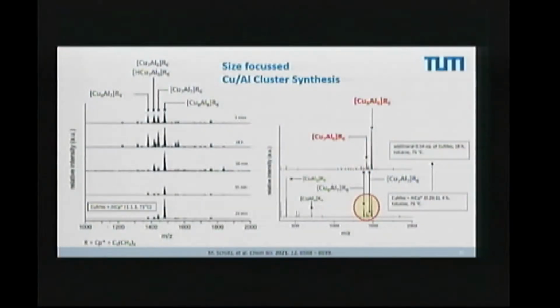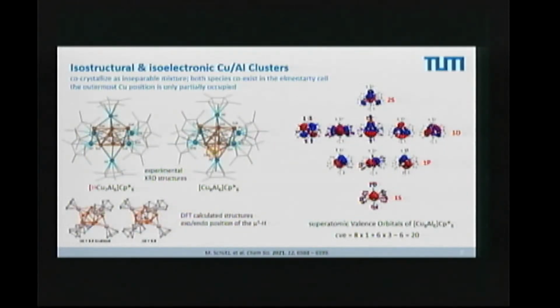And if you go from this here to there, you see a simplification of the mass spectrum. So by tweaking the conditions, by playing with the time, with the concentration range of our precursors, we can influence the nucleation and growth of the clusters in some way. At the moment, this is done by stomach feeling of the informed chemist. There is no logic. There is no theoretical guidance in this. But we can narrow down the diversity space. And if we do that, we are able to come up with single crystals of typically co-crystallizing candidates.